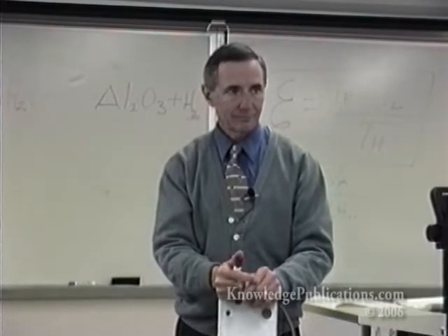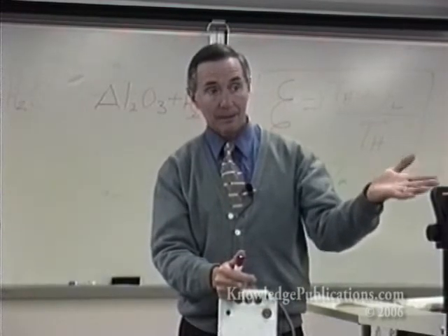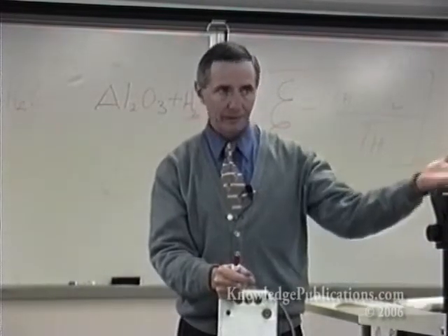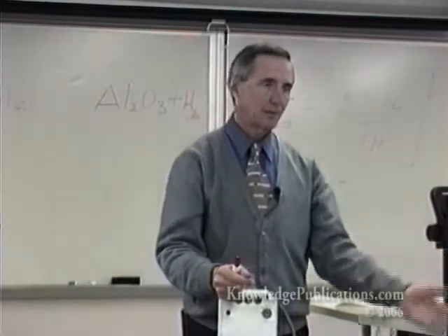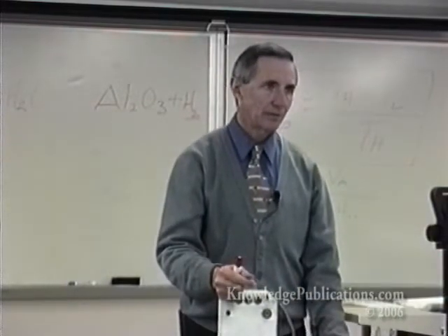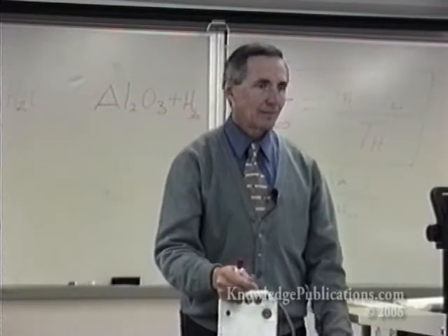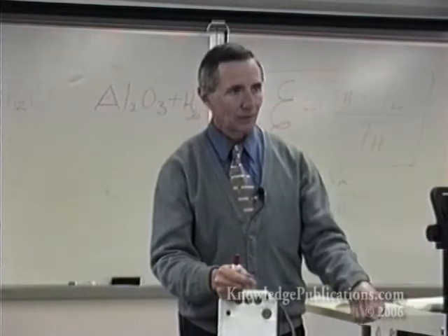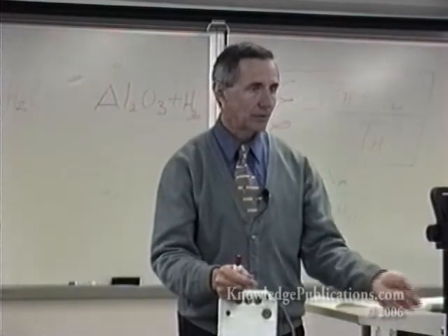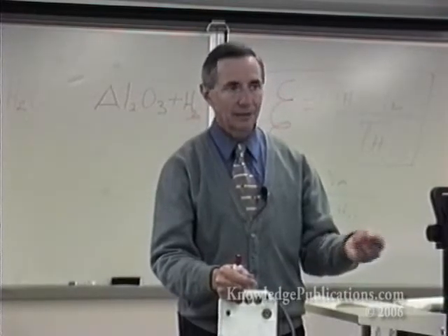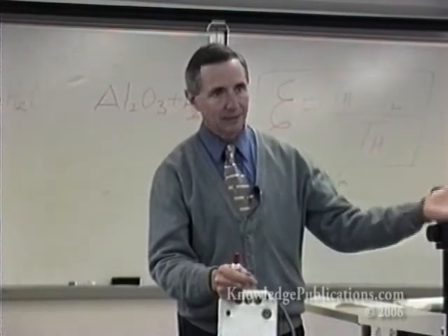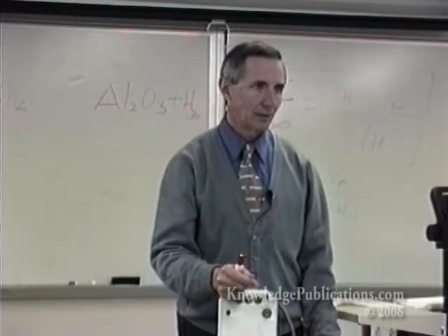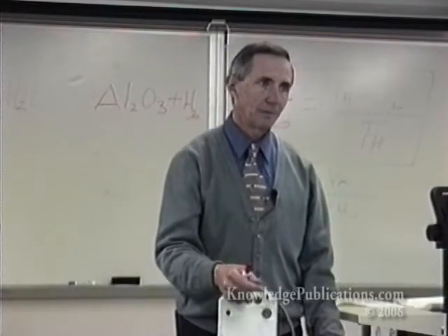But we don't know how those were welded, right? Well, here's the thing. Pipelines embrittle every day on natural gas. We find hydrogen embrittlement lots of times, less today than when I first started taking notice of it. But you can trace it. You can absolutely trace it to the conditions under which they were welded or originally produced. Wherever it occurs, and it isn't going to be every time, you just go in and replace whatever's embrittled. If you think you have a condition that's an incipient failure, you come in and bake it out.